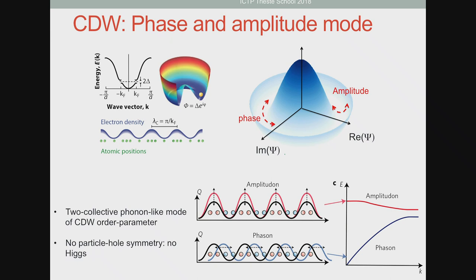So the amplitude mode is going to be called the amplitudon, or the charge density wave amplitude mode. And this is essentially a modulation of the charge density wave. So if electrons are coupled to the lattice, this modulation of the electron density will correspond to an atomic displacement. So this will be essentially a hybrid excitation between electrons and phonons. It will be a phonon-like excitation. And if you tune the phase, you will have the phase mode, and this phase mode is gapless.